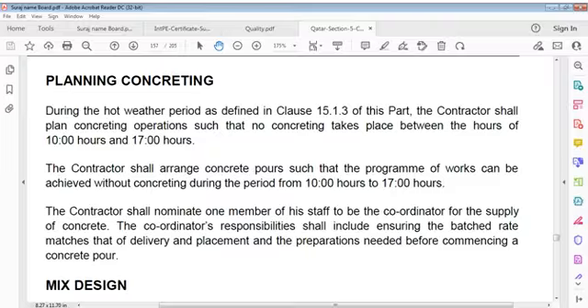Contractors shall arrange, this is time for Qatar, you can decide your own time wherever you are located, in which hours temperature remains below 40 and 35, so that concrete temperature at placement does not exceed 32 degrees Celsius and shade temperature does not exceed 35 to 40 degrees Celsius. Contractor shall arrange concrete pours such that program of works can be achieved without concreting during period from 10 hours to 17 hours.